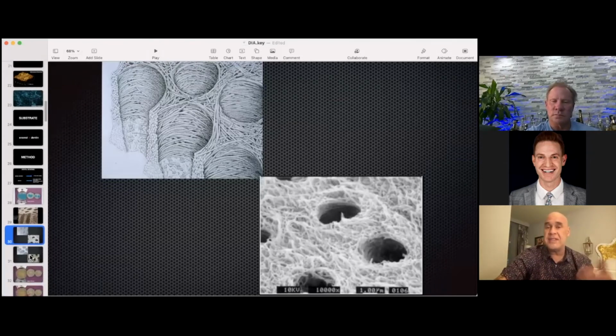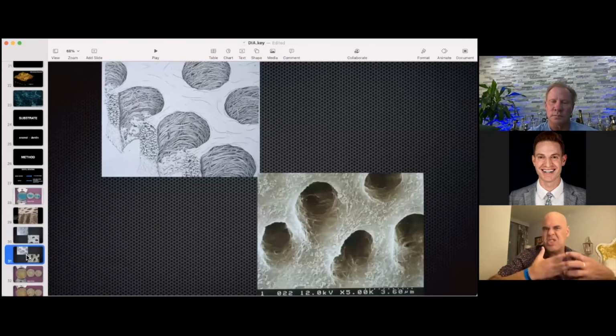What happens is that when you are rinsing your etchant and you have too much water, your first impulse is to use a little bit of air. And when you use a little bit of air, this is an image of 3 seconds of air, how the collagen collapses. Now the collagen, instead of being like a sponge, is more like a wall. It's just this collapsed wall that will hinder the ability of the adhesive to go through the collagen, and also will hinder the ability of the adhesive to seal the dentinal tubules.